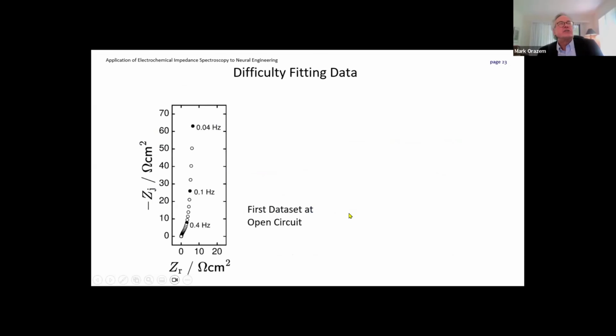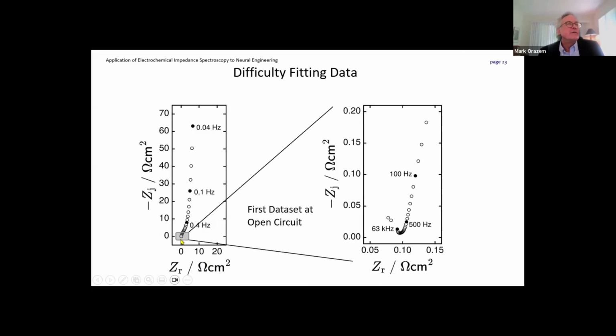There's one thing I want to mention, and this was especially true with the data that we got. All this data came from Stuart Kogan's group. And so if you look at the Nyquist plot, everything looks beautiful, but we're really missing what's happening at high frequency. If we zoom in, we see that there's high frequencies over here. This funny little loop over here, we will eventually discover is related to the ohmic impedance.